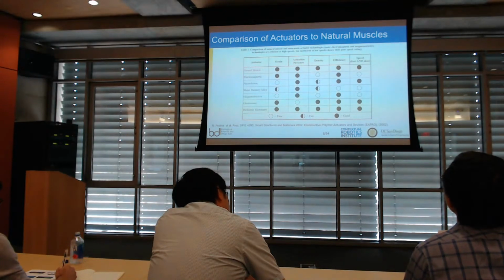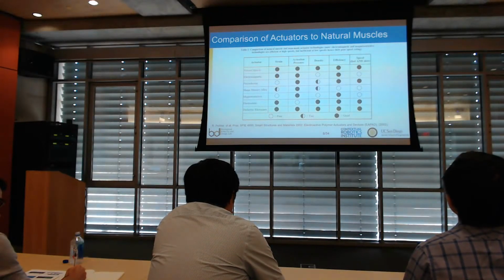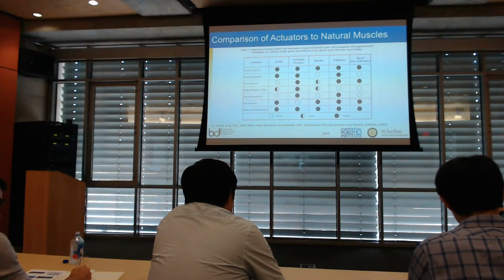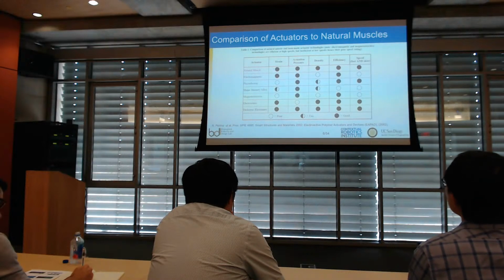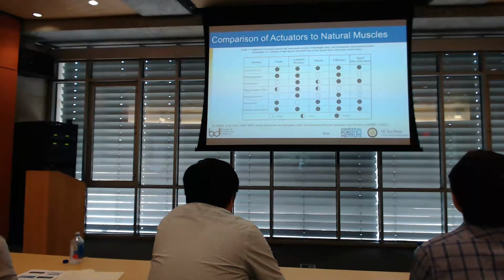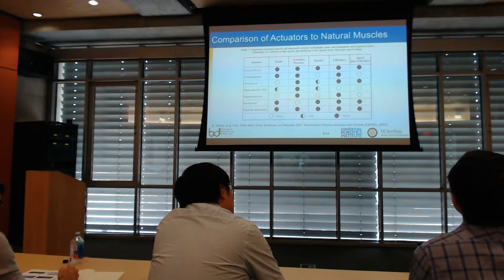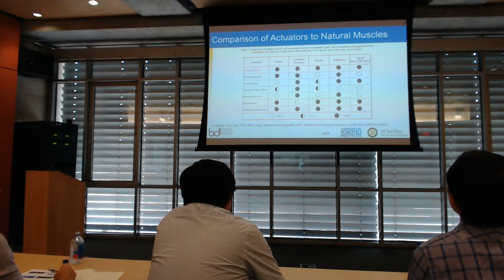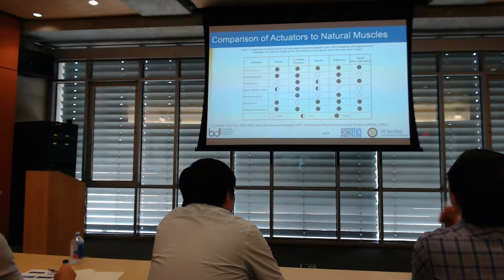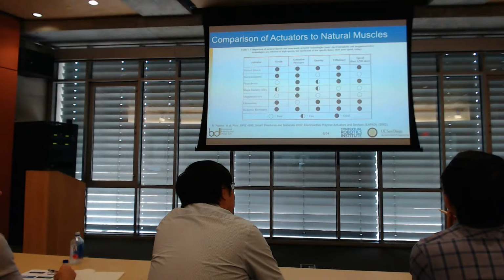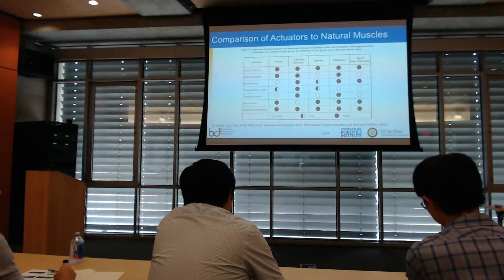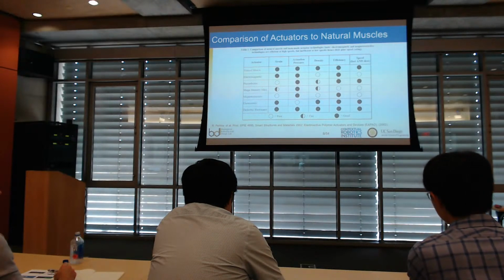So then if you look at some of the other types of actuators that people use, like electromagnetic, it's good for strain and pressure, so you can get a lot of pressure with motors, for example, but they're very heavy, so they're very dense. And also they work better at high speeds than low speeds, so they're not as efficient at a broad range of speeds like natural muscles. But if you look on the bottom where we have dielectric elastomers, they have similar performance as natural muscles. So it's a good choice for making artificial muscles for soft performance.